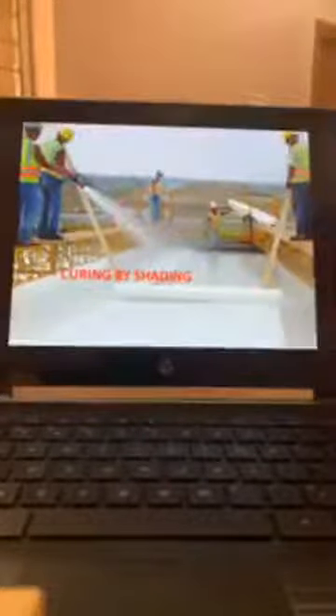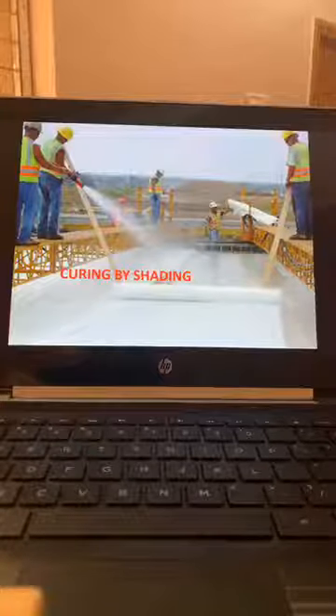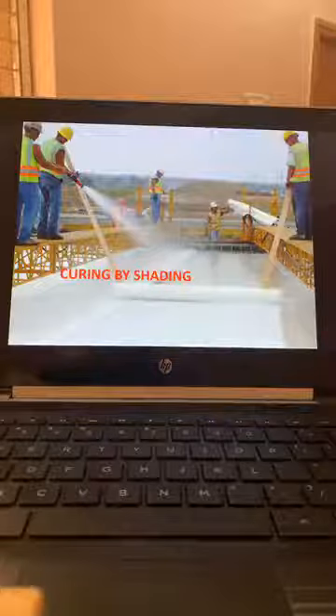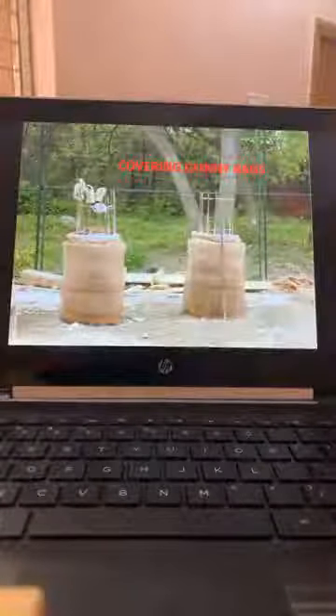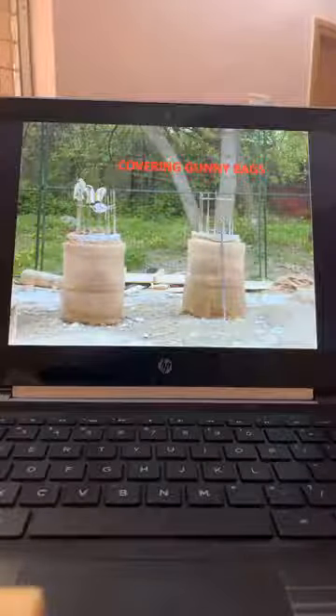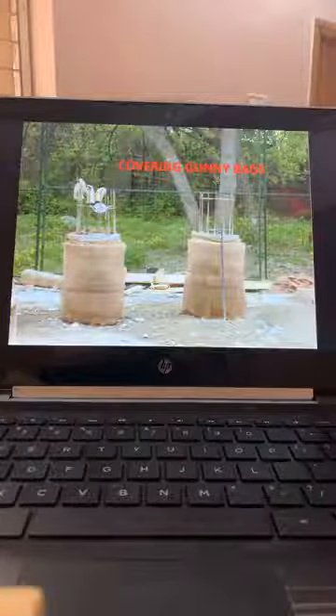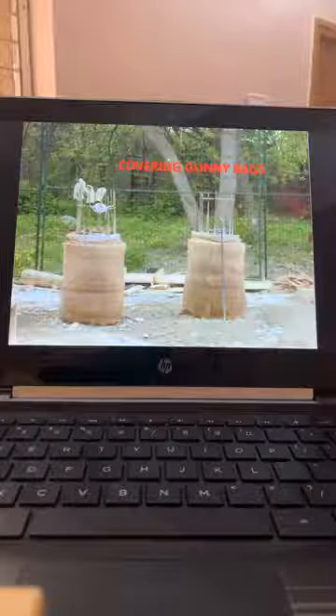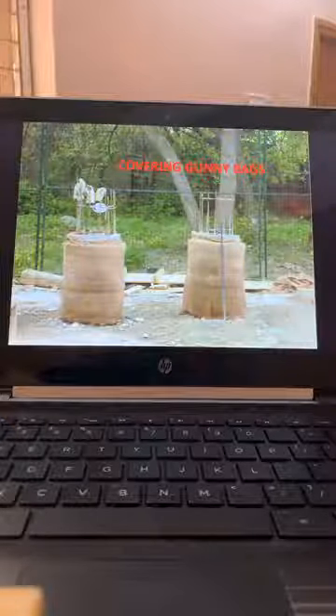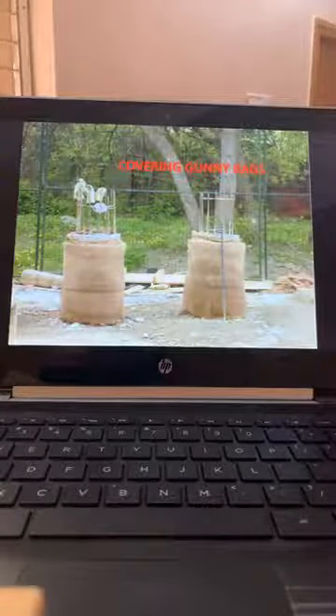This membrane has to be breathable — air has to go into the concrete because the chemical reaction has to continue. We use membrane curing where water application is not possible, such as elevated expressways or metro structures. Shading is another form. For columns, covering with gunny or jute bags is preferable for vertical surfaces where it is difficult to maintain moisture. You spray water on the jute bag and it retains moisture — even if you cure once every six hours it is sufficient, otherwise column surfaces dry very quickly, especially in a dry climate like Hyderabad.